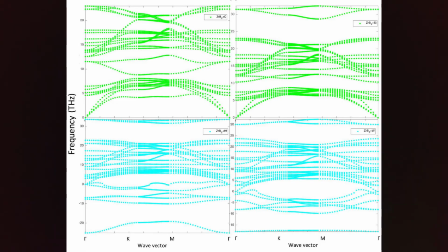This graph shows zirconium diboride with impurities: carbon, silicon, hafnium, and tungsten. The carbon and silicon impurities show dynamical stability similar to the perfect structure, but in addition to the dominant acoustic mode, there exist more low frequency optic modes. Hafnium and tungsten, as seen in the graph, have low frequency compared to carbon and silicon. The added optic modes for silicon are at relatively higher frequency than carbon, as seen in the graph.